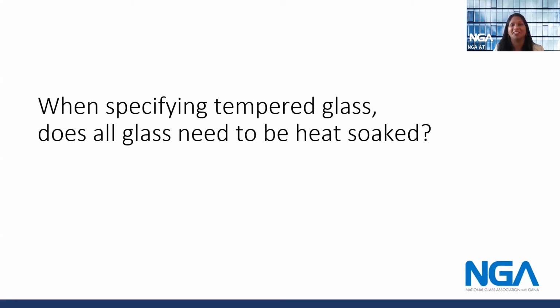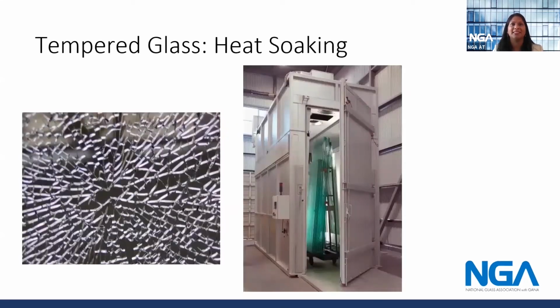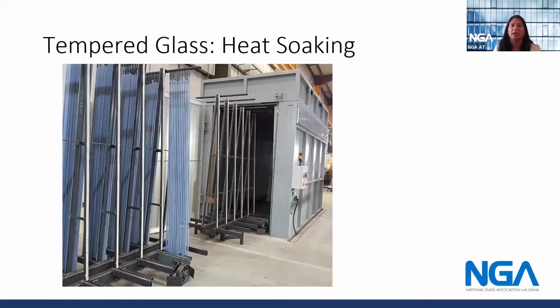So heat soaking, a very controversial topic. It's important to know heat soaking in glass. So there's basically two testing approaches. Heat soak in each light, some people require each light to be tested, whereas others use a statistical approach. So the statistical heat soaking testing involves a statistically significant number of glass panels to be tested, as opposed to 100% for a project. It is important to recognize there isn't a consensus. Should you have 100% of testing, or just a portion of the testing.